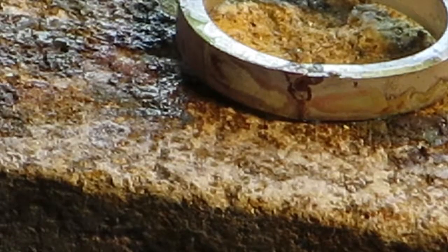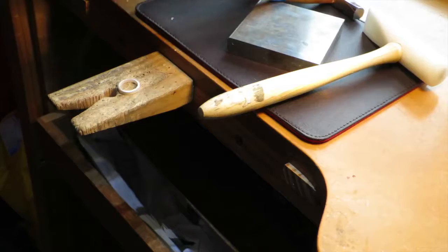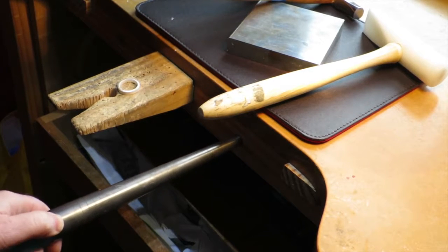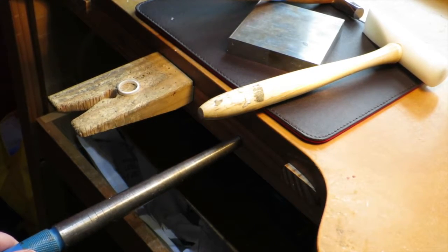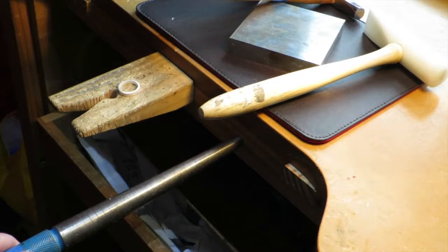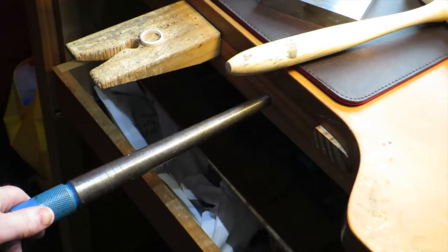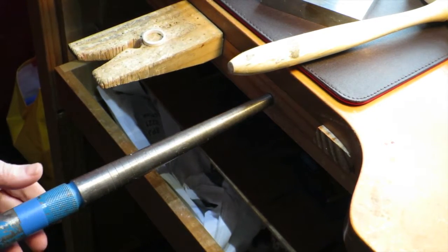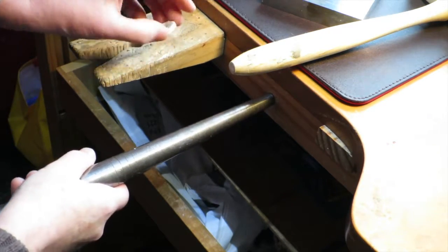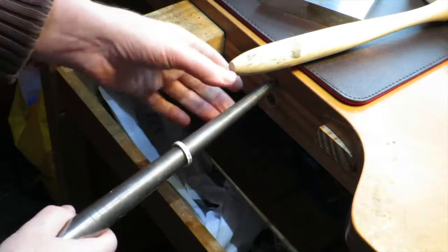There, you see it run? So, the opposite of annealing, please. Let it cool down on the block. Do not put it straight into cold water, because you will shock the joint and it could crack open. Also, you've been at 770 degrees centigrade. If you throw it into cold water at this point, you will make your metal brittle.